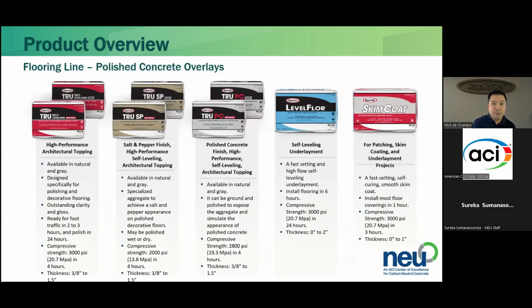We picked out another set of packaged products here. This is what we call our flooring line. It's a line of self-leveling products. And this started out as a single self-leveling underlayment product, but as contractors quickly picked up on the fact that CSA allows for rapid hardening materials, or rapid hardening overlays, and has low shrinkage, they found it great for polishing and making polished concrete overlays. And that one product turned into an entire line of products.